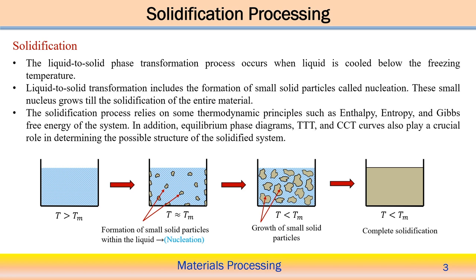But how can we explain the solidification? Initially, just follow this figure. Initially there is a liquid metal, and its temperature is above the melting point temperature. Now it gets the favorable conditions, that means if we extract the heat from this container, then nucleation at one particular position transforms the liquid phase to the solid phase through the formation of a nucleus. That is called nucleation, and it starts forming approximately near the melting point temperature.